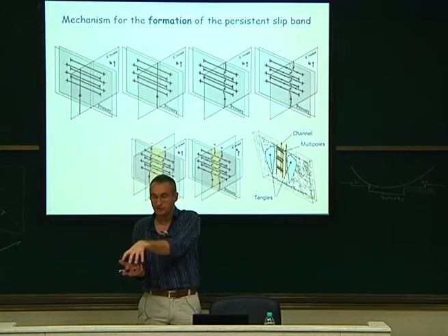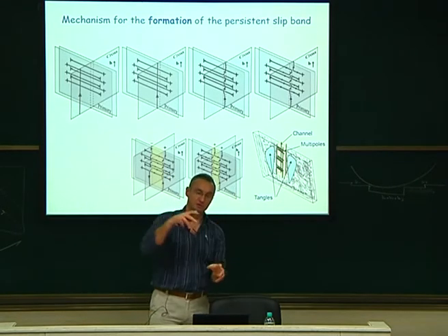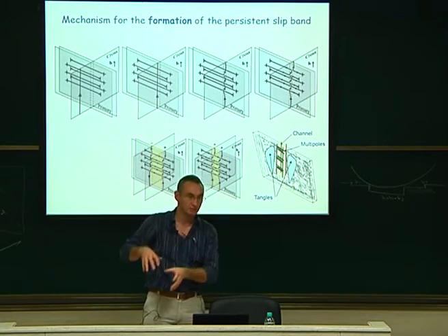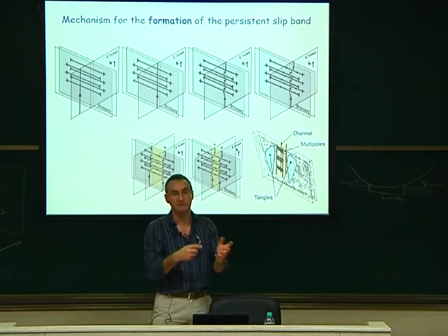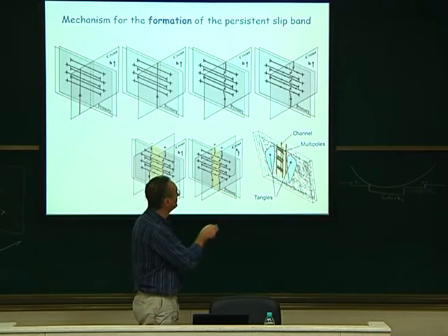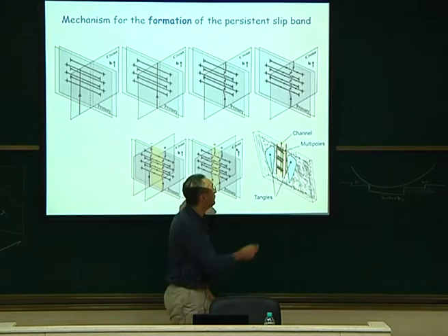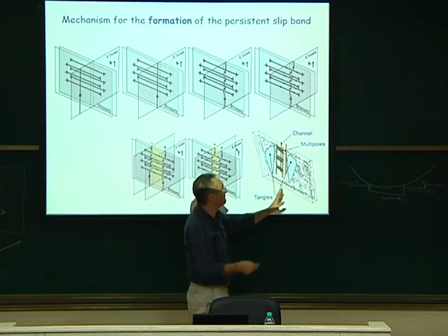So you can have a dipole here. The next one will be at a given distance, and the one there. And when you cut with your dislocation, it will create the prismatic loops at the location where the dipoles were, where the vein was. You see? So here, if you had the vein here, another then there, then you will have the prismatic loop here. But now those loops can move, so they don't stay there, they can glide, okay?